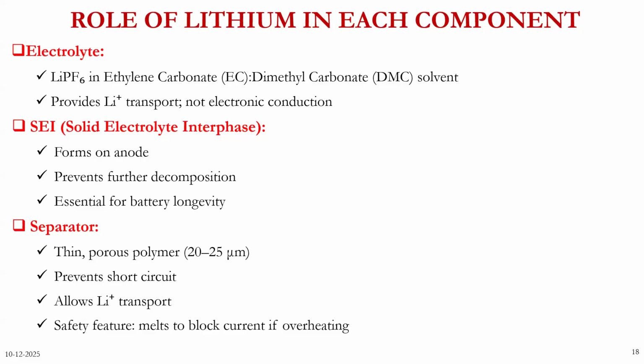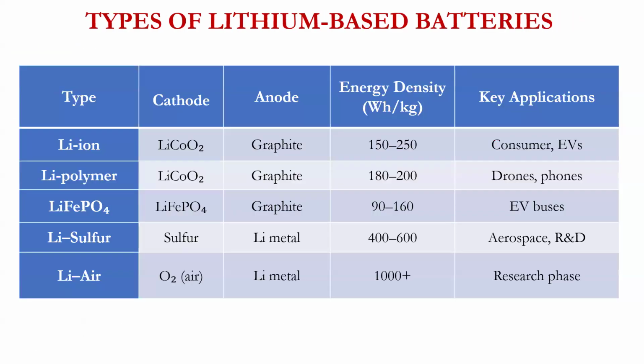And we have one separator. The separator is generally very thin, around 20 to 25 micrometers of porous polymer. It is used for preventing short circuits and allows the transport of the lithium ions. It is also used for safety purposes, wherein it melts to block current if there is overheating.